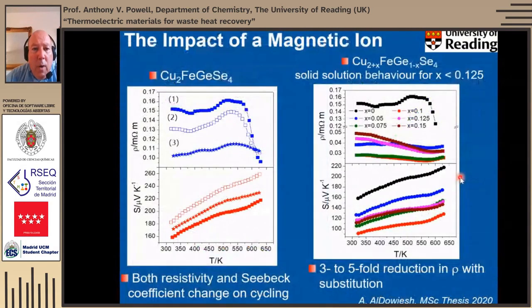So then we thought, well, what happens if we replace that zinc with a magnetic ion? Because there have been some studies which suggest that if you have a magnetic ion there, the effective mass of the carriers, due to coupling between the electron and the magnetic moment, increases, and that can actually be beneficial for the Seebeck coefficient. So we took this end member phase, and we essentially tried to do the same process with it, replace the germanium-4 with some copper, which causes the copper to oxidize to copper 2+ and introduce more holes